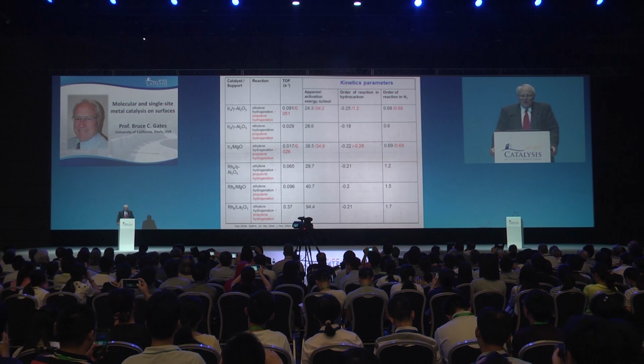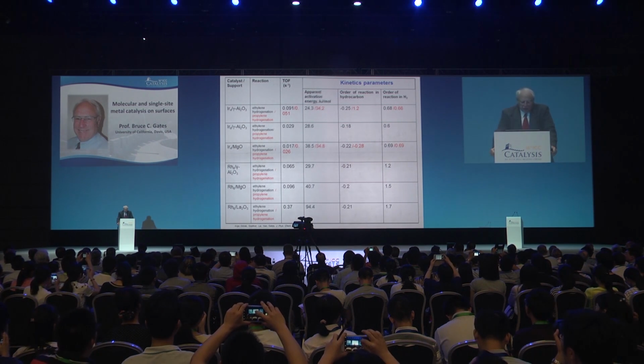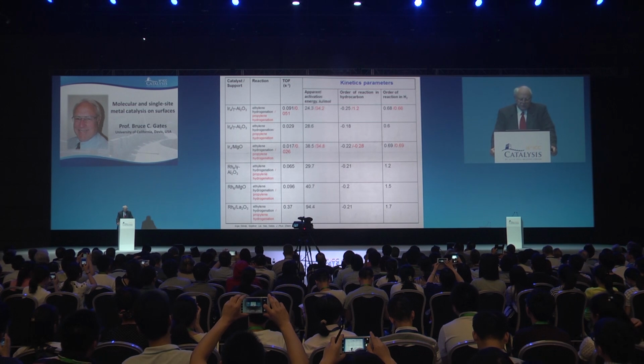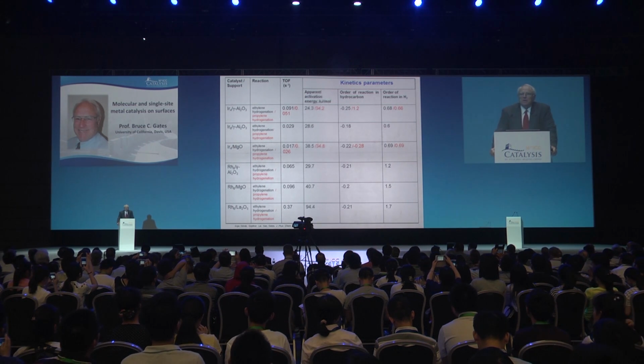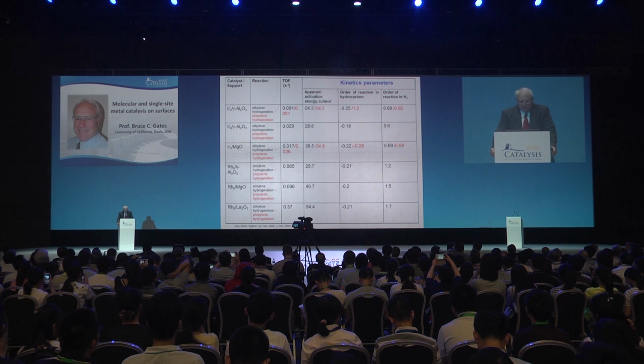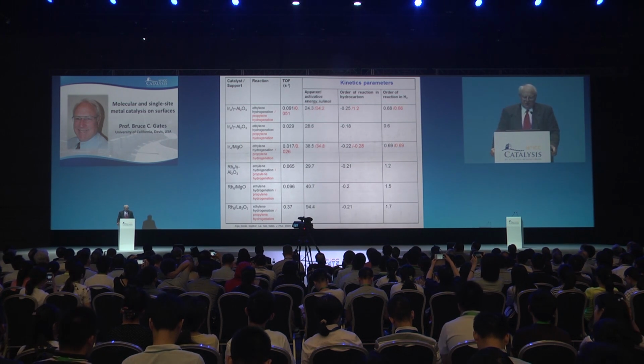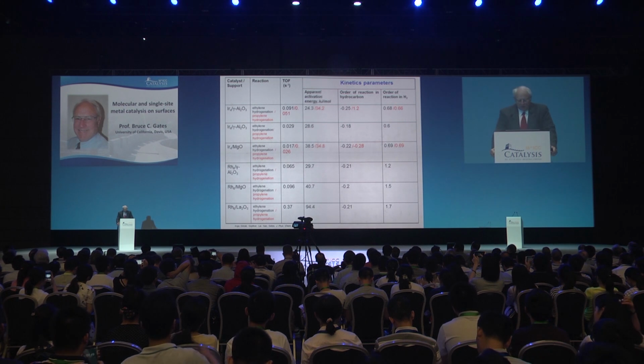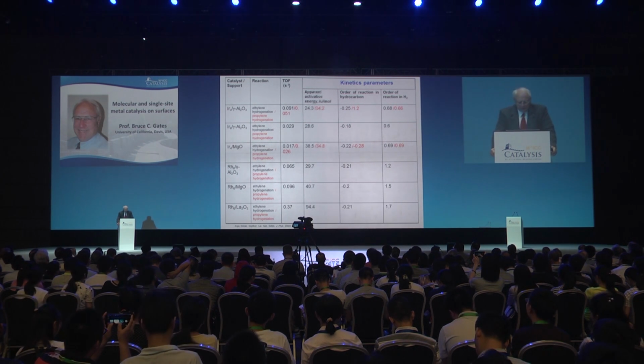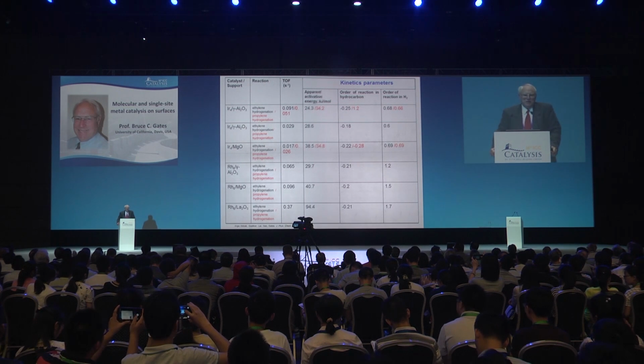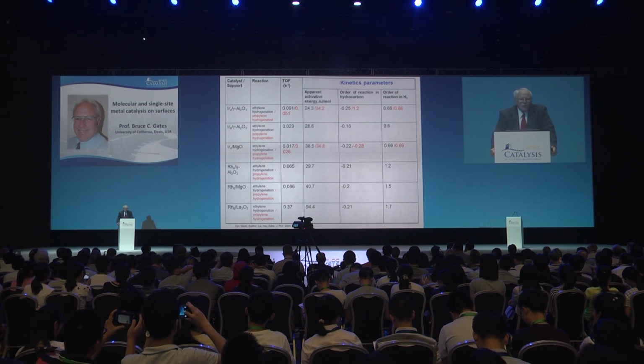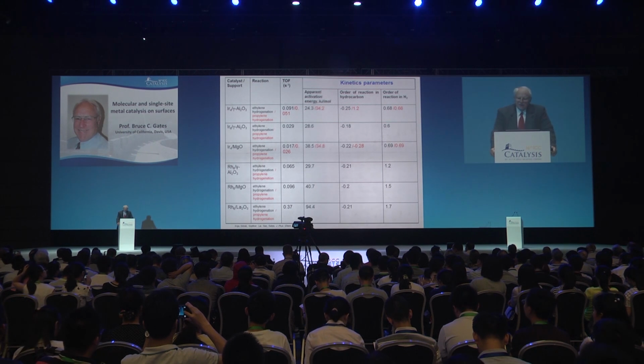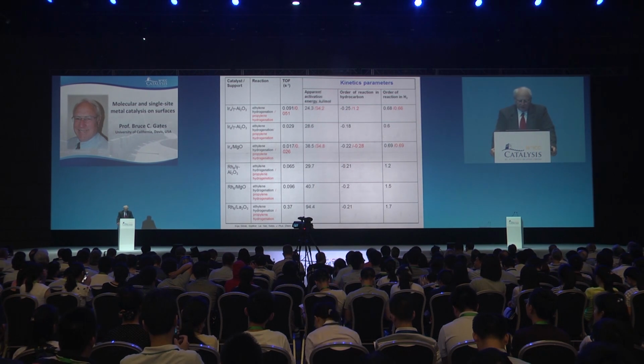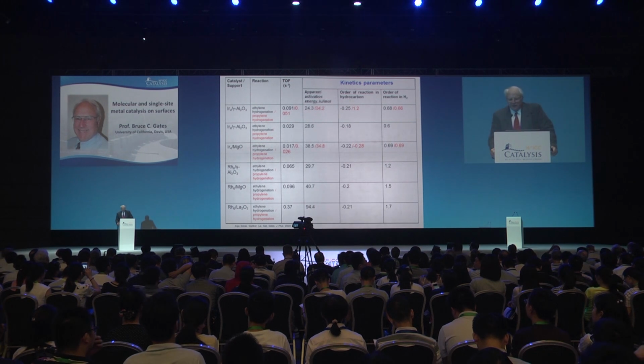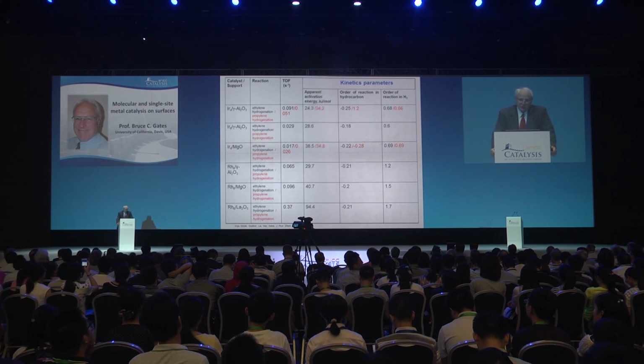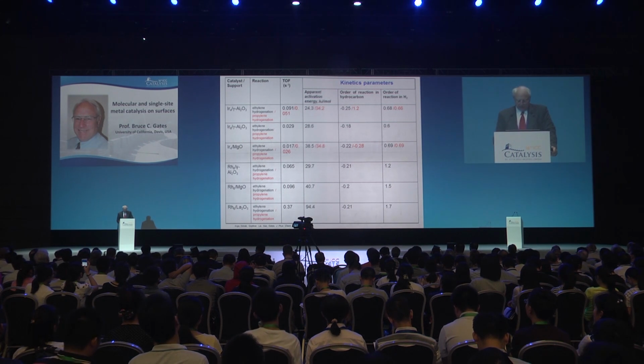There's a lot of work that's been done earlier trying to characterize the supported cluster catalysts using reaction kinetics combined with various spectroscopies. I don't want to take the time to go over this. There's a lot of information, and you can see it quickly, but you won't see all the patterns. The point I want to make is that there are not always such simple patterns in the kinetics parameters characterizing ethylene hydrogenation, propylene hydrogenation, toluene hydrogenation for this class of catalysts, various metal clusters on various supports.